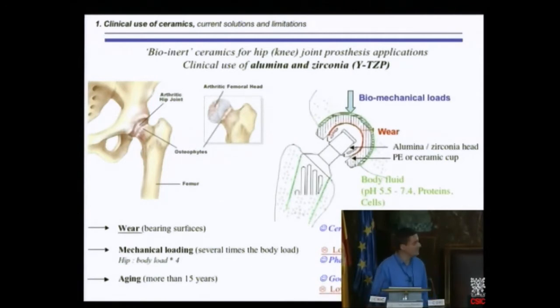So the specifications are quite demanding, because we use ceramics for the femoral head and for the cup, and so we have to resist wear, so that's the first issue and the main issue in orthopedics. So these are two bearing surfaces. As we said before, ceramics are well suited since they have low roughness, also low wetting angles, high hardness, so low wear rate. We have also to resist significant mechanical loading, especially when you are walking or running.